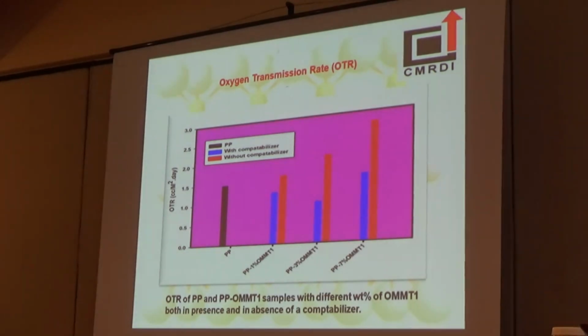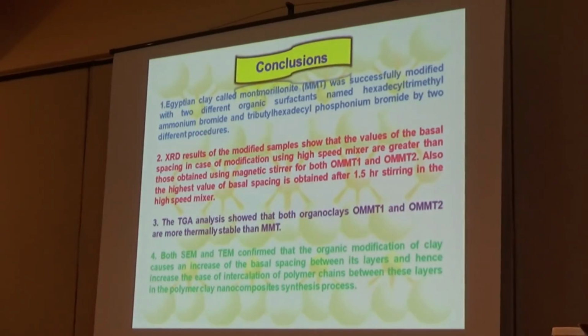Oxygen transmission rate also decreases by increasing the amount of organically modified clay in all the prepared series. Conclusions. Egyptian clay called montmorillonite was successfully modified with two different organic surfactants, hexadecyl trimethyl ammonium bromide and tributyl hexadecyl phosphonium bromide. XRD results of the modified samples show the value of basal spacing in case of modification using high-speed mixer are greater than the magnetic stirrer.